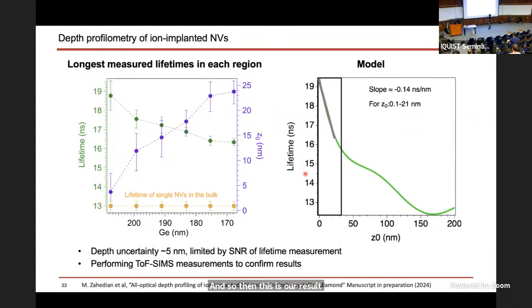Basically, we took the longest measured lifetime in each region. The thicker the germanium implantation mask, you expect the ions to be the shallowest, so the NVs to be shallowest, and therefore correspond to the longest lifetime. And then as you decrease the thickness of the germanium mask, you expect the ions will go deeper into the crystal, and therefore your lifetime will decrease.